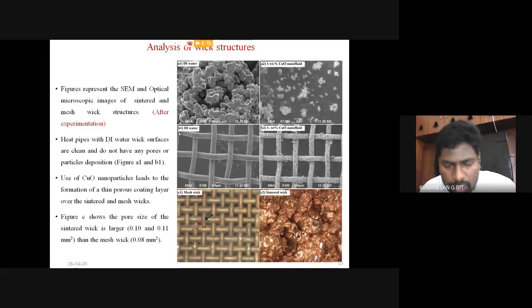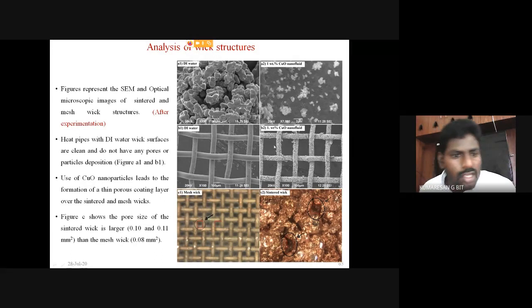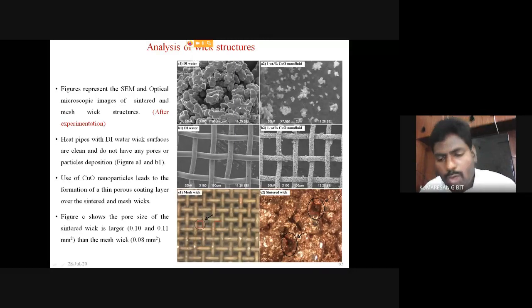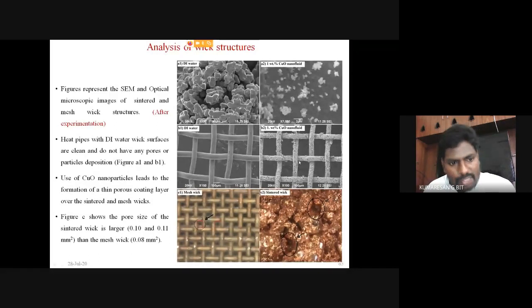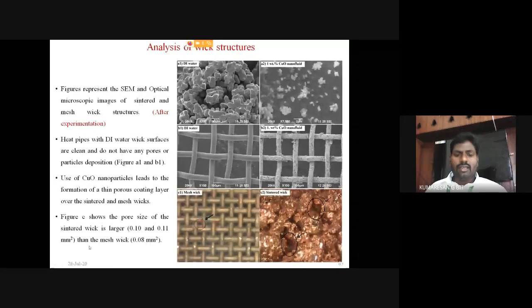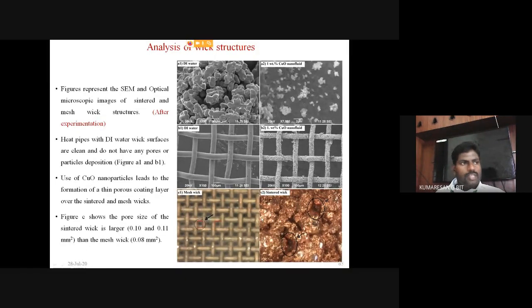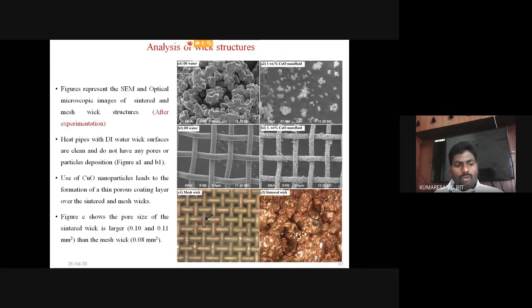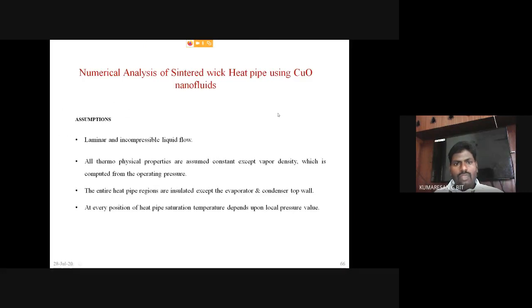Okay, so the B1 image is very clear. There is a mesh wick structure, the image is very clear. But in the B2 image, the use of CuO nanoparticles in the base fluid creates some pores over the wick structure. This figure C shows the pore size of the sintered wick is larger than the mesh wick structure. Okay, so if the pore size is high, it can allow more fluid to flow over it. The next one is the two-dimensional numerical analysis of sintered wick heat pipe.